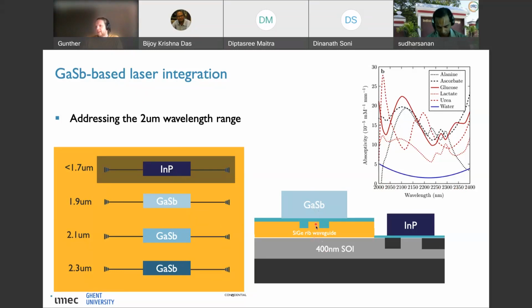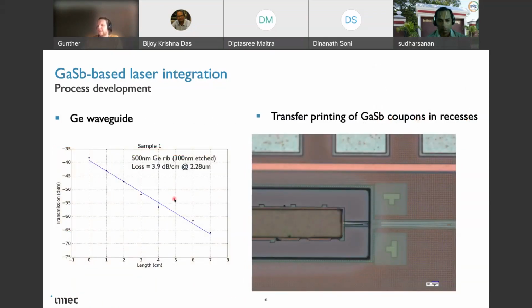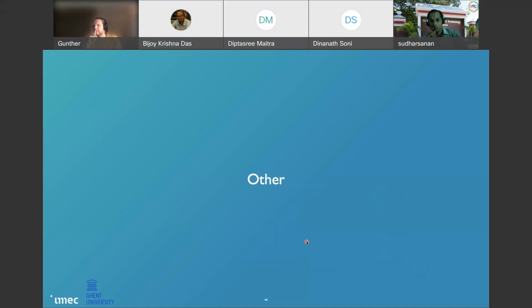For the optical coupling, we actually need silicon germanium waveguides instead of silicon waveguides because of the higher index of the germanium. And we also need, of course, to be able to transfer print gallium antimony. So this is under development. At the moment, we have germanium waveguides with reasonable losses, about 4 dB per centimeter. And we were also able to demonstrate the first transfer printing of gallium antimony, in this case still dummy coupons in such a recess on a silicon photonic stamp. So that was the 3.5 activities.